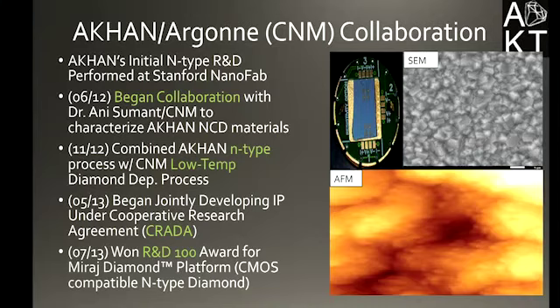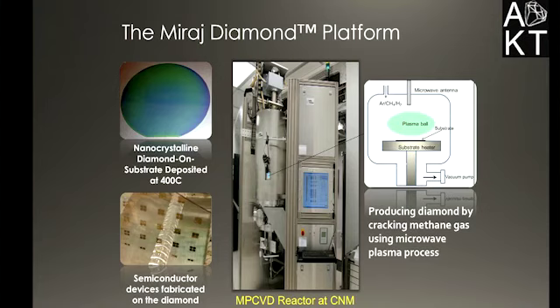And a few months later, we were successfully able to combine this N-type process with a low-temperature diamond deposition process. And shortly after that, we began jointly developing this technology under the Cooperative Research and Development Agreement. And if we look very closely at the nano level, we don't see these pits of these crystallographic dislocation sites. We actually see protruding aggregates, which were not shown to be adverse to the electronic characteristics. And shortly after making these announcements, we actually won an R&D 100 award on this technology.